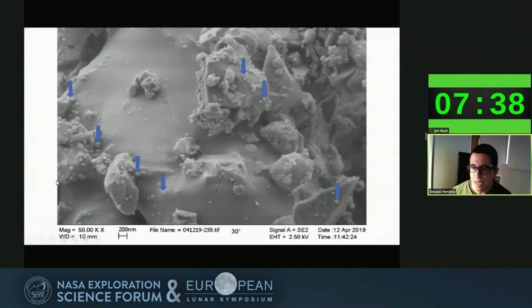Under SEM, we see all these little blebs on the surfaces of the grains, and these are metallic iron. There was a paper by Allen et al. 1994, which used a similar method to ours, and they were able to determine through SEM and Mossbauer spectroscopy that these little blebs on the surfaces of the grains are metallic iron. And this is an SEM image of JSC1A grains.